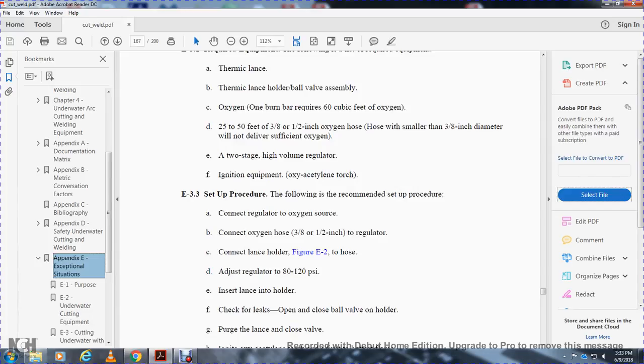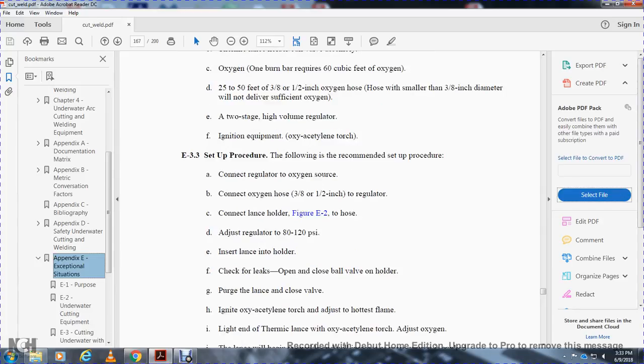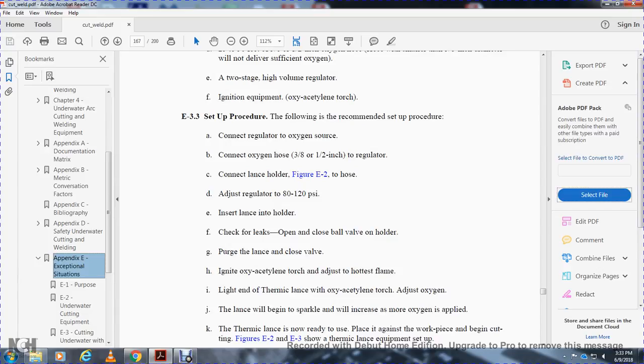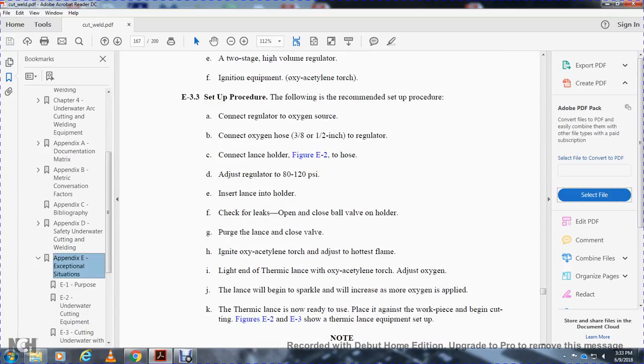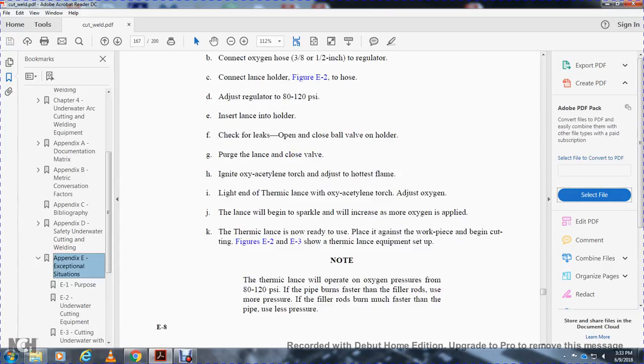E3-3, setup procedure. The following setup procedure is recommended: connect the regulator to the oxygen source, connect the 3/8 to 1/2 inch oxygen hose to the regulator, connect the lance holder, as in Figure E-2, to the hose, adjust the regulator to 80 to 120 psi, insert the lance into the holder, check for leaks, open the ball valve on the holder, purge the lance and close the valve, ignite the oxyacetylene torch and adjust to the hottest flame. Light the end of the thermic lance with the oxyacetylene torch and then adjust the oxygen. The lance will begin to sparkle and will increase as more oxygen is applied. The thermic lance is now ready for use. Place it against the workpiece being cut. Figure E3 shows the thermic lance equipment setup.